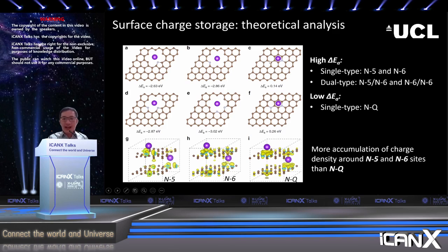What we found out is that for a single typed nitrogen doping material, where we only have either nitrogen 5 or nitrogen 6, it shows a very high adsorption energy. For dual typed carbon material, where both nitrogen 5 and nitrogen 6 are present, the structure shows also very high adsorption energy towards potassium ions. But for the single type nitrogen Q, the adsorption energy is relatively low compared to the other two types of nitrogen doping. So it explains why the 650 degrees sample has the best performance, because this sample has the highest amount of both nitrogen 5 and nitrogen 6 dopants, and the lowest nitrogen Q dopant compared to the other two materials.